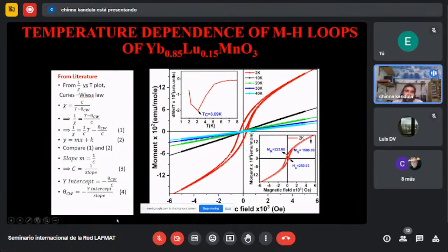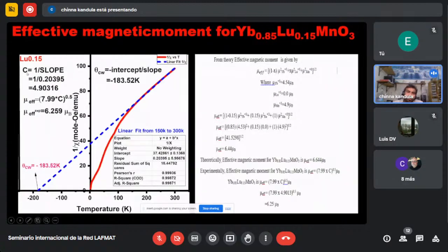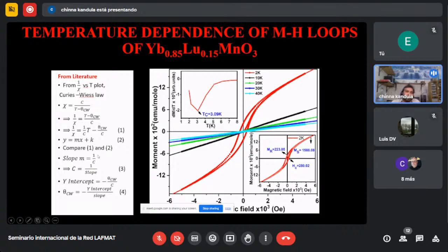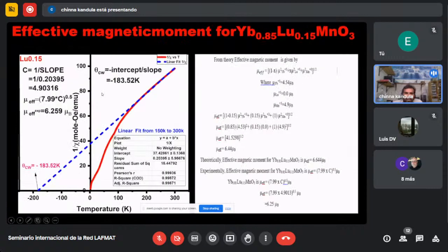So this is the theory. Why am I taking it like this? Why do I get C as 1 over the slope here? I will explain from the literature. We know the Curie-Weiss law: chi is equal to C over T minus theta W. If we take the reciprocal, it comes in the form y equals mx plus c. Here I show equation 1. Comparing with y equals mx plus c, it is a straight line with an intercept. So the slope is 1 over C, and the y-intercept is theta over C. That means 1 over C is the slope, so the Curie-Weiss temperature is equal to minus the y-intercept divided by the slope. That's how I calculated the theory.